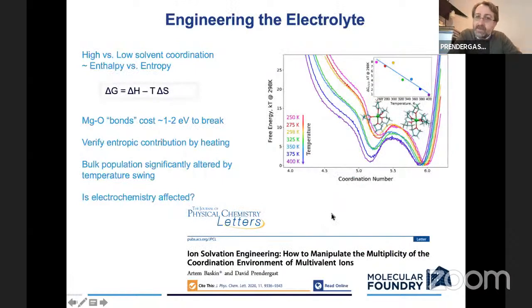Okay, I mentioned entropy a little earlier. One way you can think about modifying your electrolyte population would be by changing the temperature, because if certain free energy minima have, let's say, lower enthalpy of binding, but they are on an equivalent scale of free energy to the higher enthalpy of binding species, then they must have quite a large entropy component in their free energy. And therefore, if you change the temperature, the slope of this free energy is defined by the temperature, by delta S times T. If you vary it, you can alter the free energy significantly, and therefore switch from one dominant population to another by increasing the temperature. The more entropy stabilized objects will become more stable at higher temperatures.